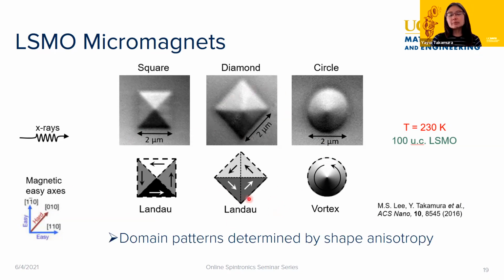And even though with a diamond-shaped one it looks like you only have 2 domains, that's because the projection of these domains in the direction of the X-rays are the same, so we can't actually distinguish. But we've rotated the sample. We know that we really do have a Landau structure with 4 domains, as in the schematic. And the circle is a vortex, where you see this gradation of color going from white to black in the circle.